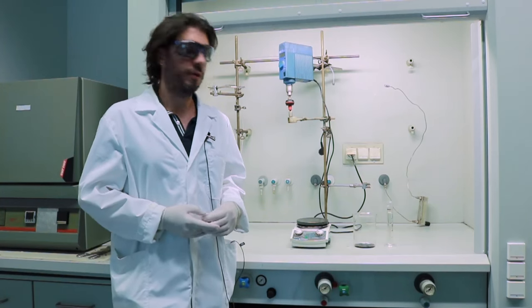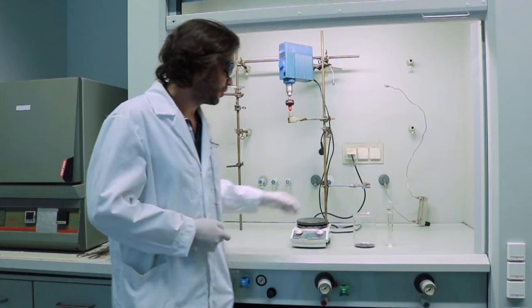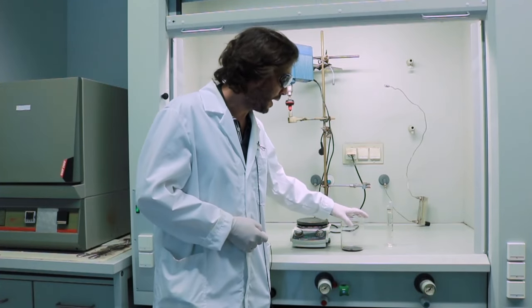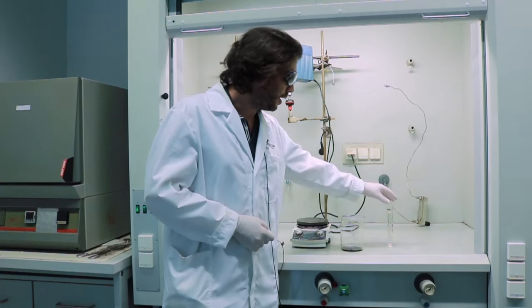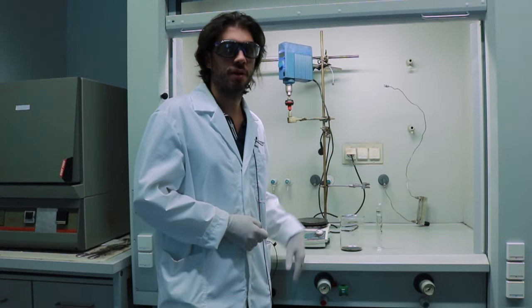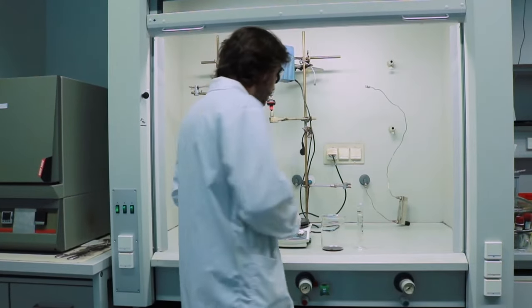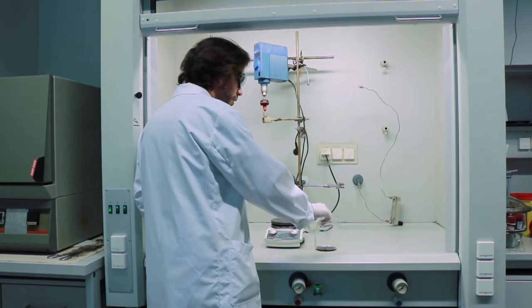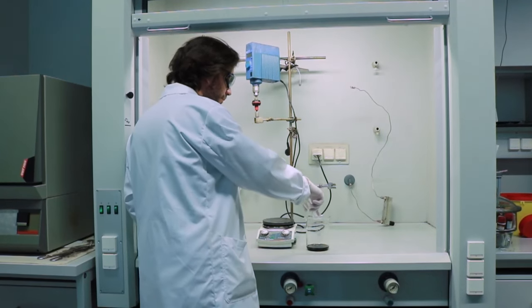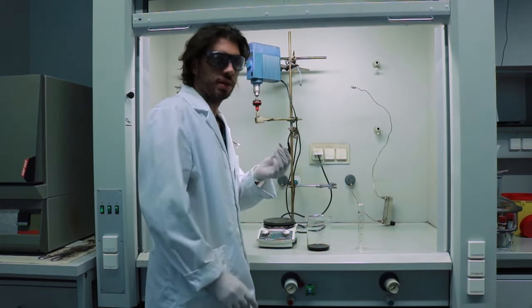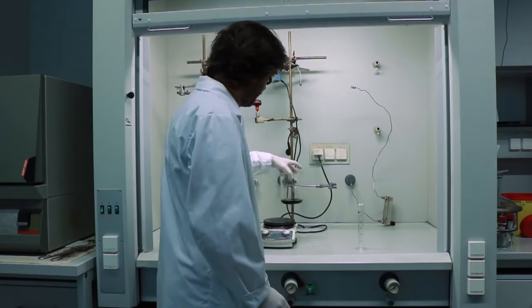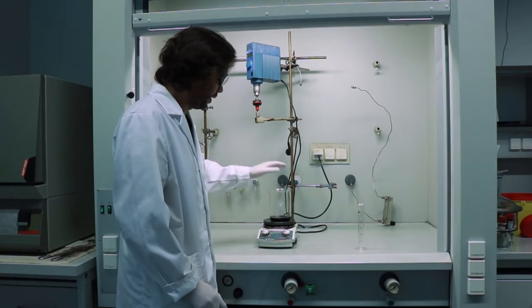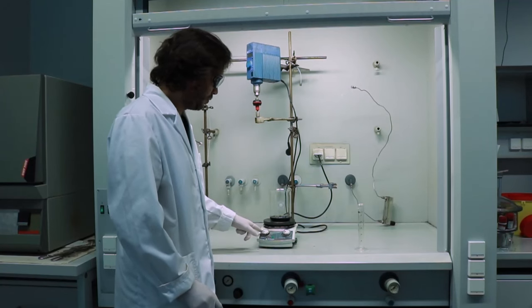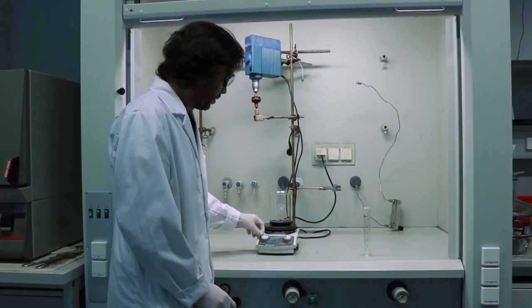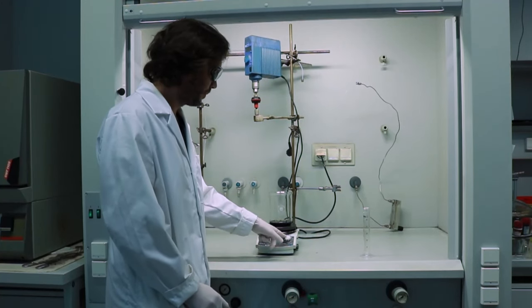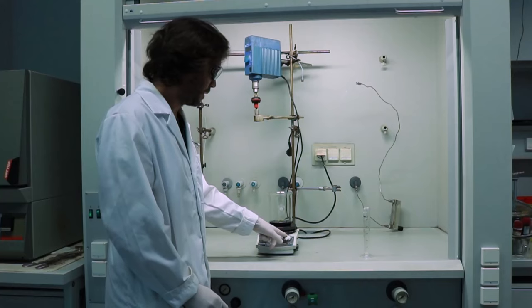The experimental setup for the combustion synthesis is very simple. So we have here a mixture of the nitrate salts and the fuel, and here are 50 milliliters of deionized water. So you just pour the water in the beaker, you add a stir bar, and you put it on the heating plate. Then you just set the heating to maximum and you also start stirring.